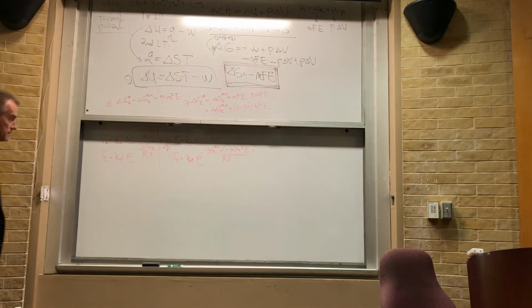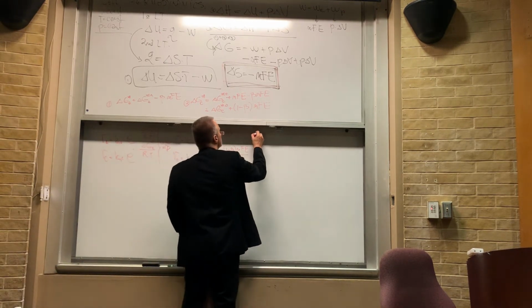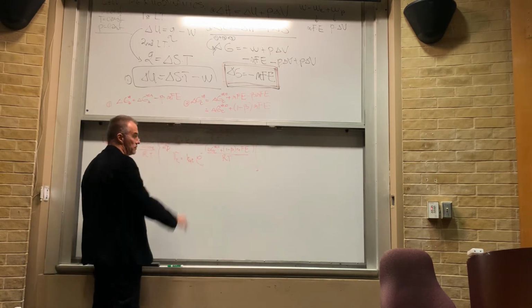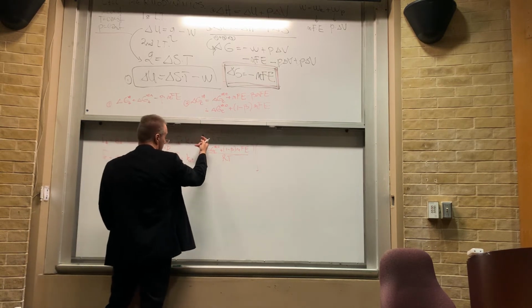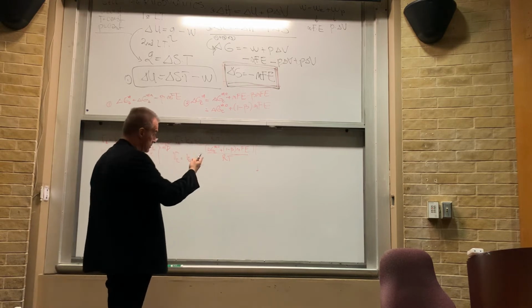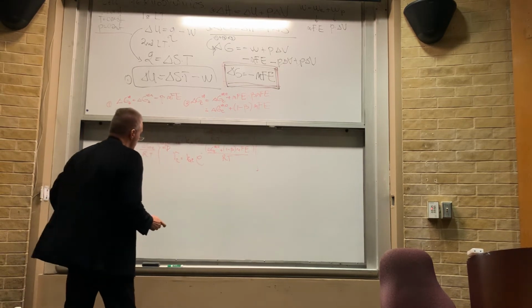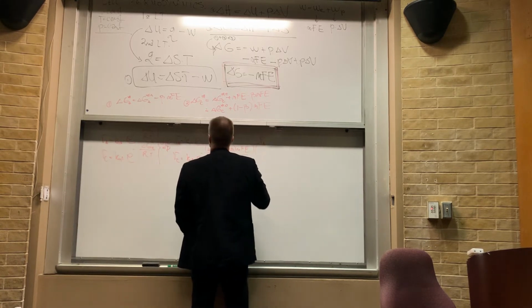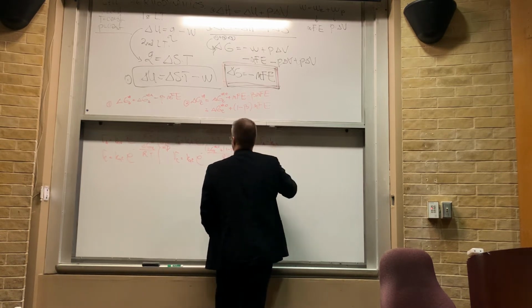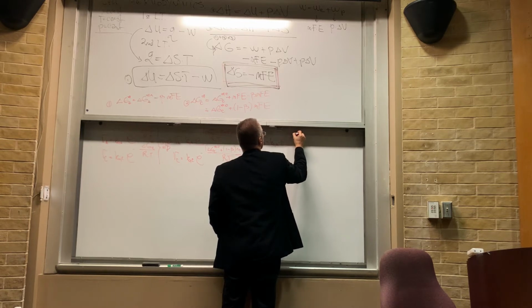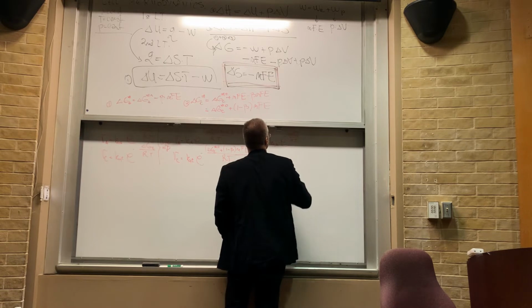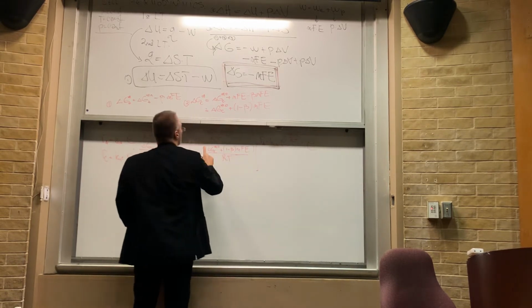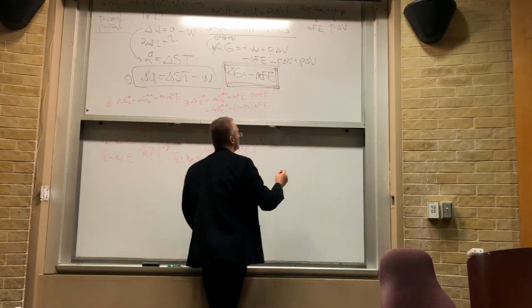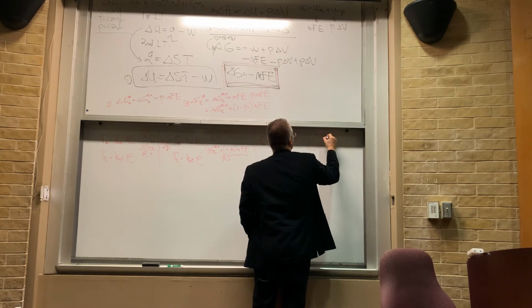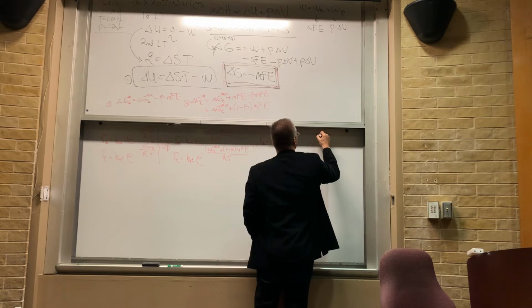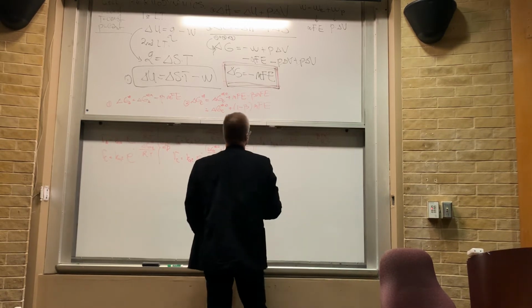This is beautiful because it helps us further simplify the situation. If I expand these exponents, where I have this minus, I'm going to just move it in, get rid of the brackets and put this into a product. So it's going to look like this. R_A, which is the rate of the anodic reaction, is equal to k_0A e to the minus ΔG‡_0A over RT times e, this minus and this minus gives you plus, there's going to be βnF over RT, all right? Times e.